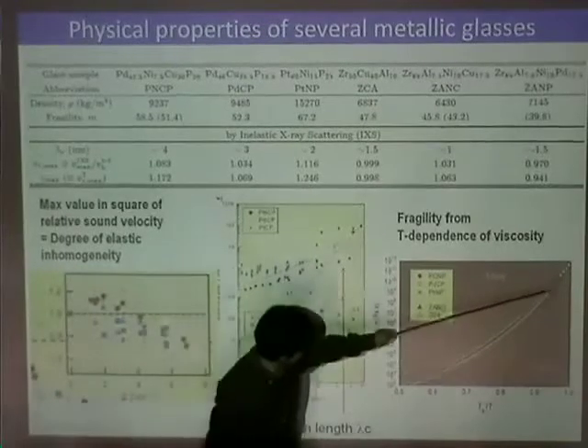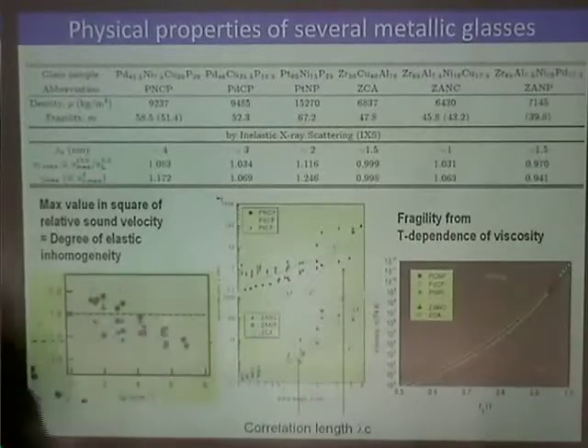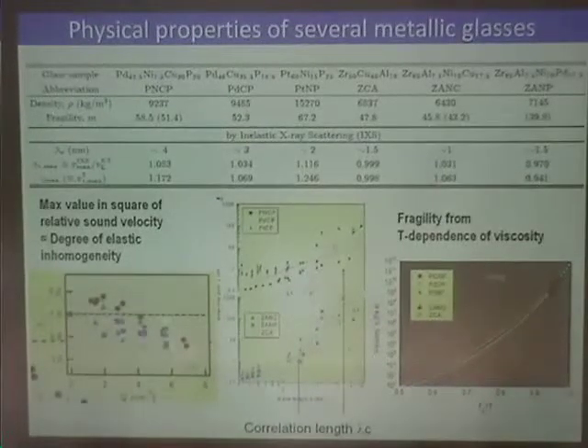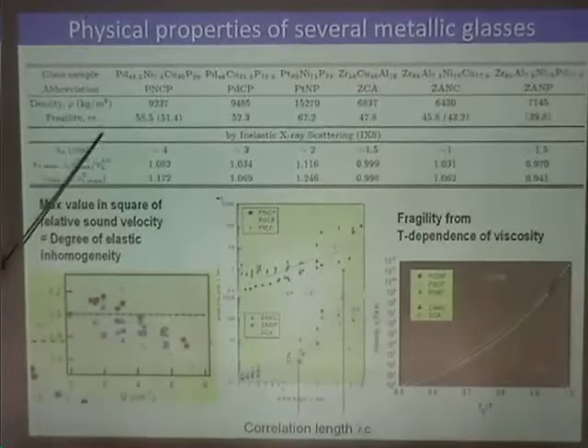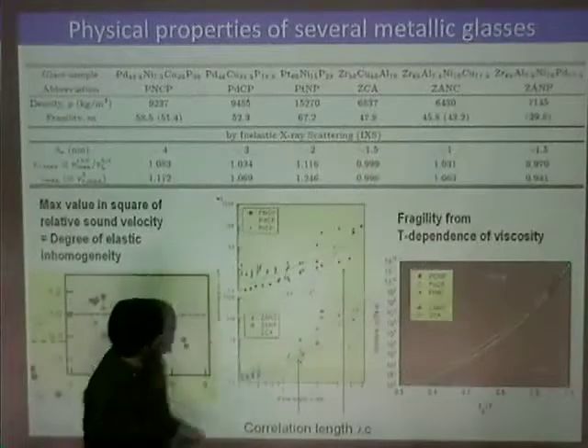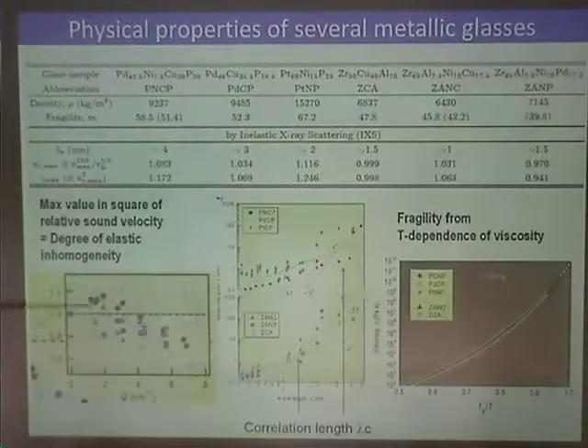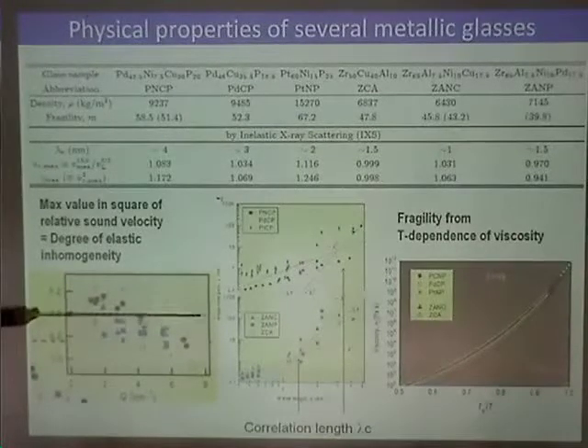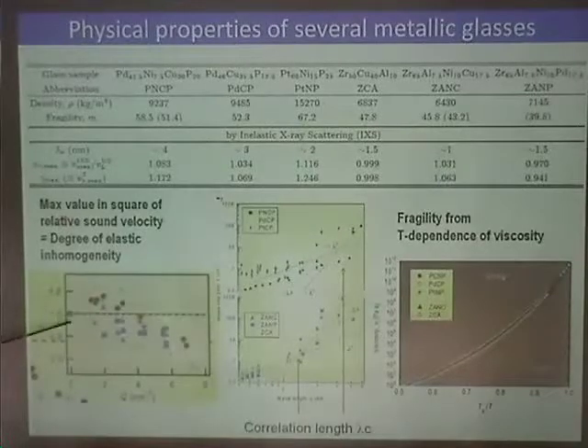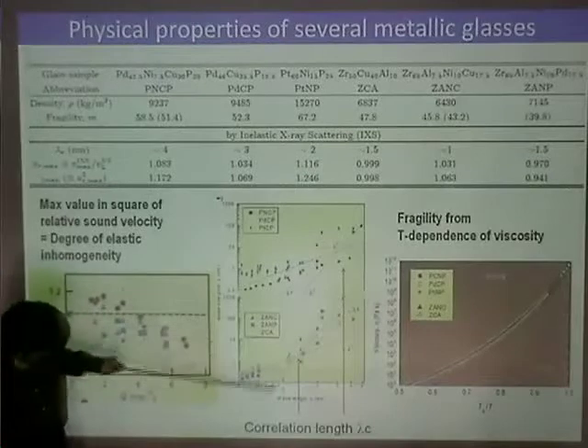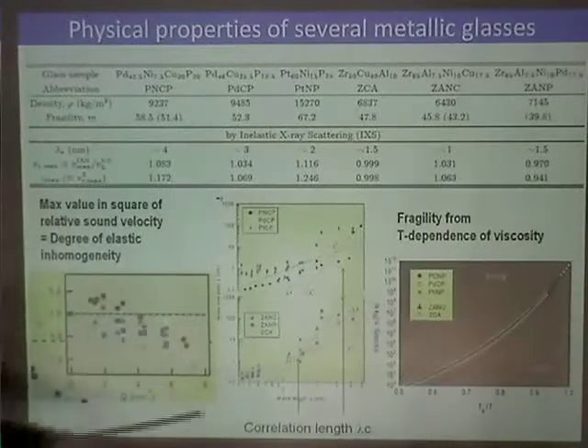Furthermore, we have measured the viscosity of the 6 types of metallic glasses. The fragility of these 6 metallic glasses is listed here. And we have defined the deviation from the average as the degree of elastic inhomogeneity. And the critical point, for example, is defined as the correlation length.